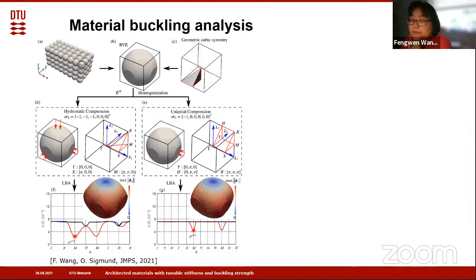We employ Bloch-Floquet boundary conditions. Numerical simulation shows we don't have to search through the whole k-space. We only need to search all the k vectors along the irreducible Brillouin zone edge indicated by the red lines. Then we can get the band structures. Then the material buckling strength is determined by the lowest critical buckling factor here. One thing I have to mention: depending on your load conditions or your macrostructure geometric symmetries, the irreducible Brillouin zone can be different.